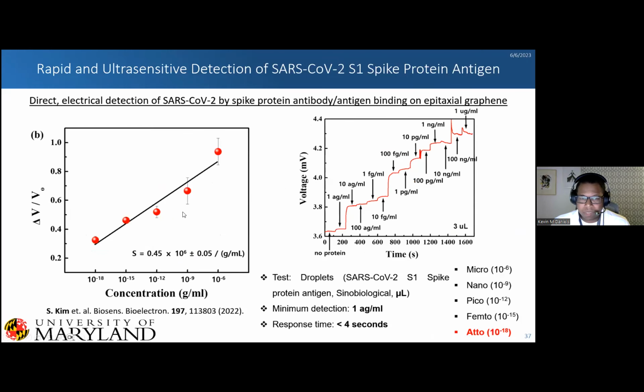And then how we can look at this is that we see a drop in our significance, our figure significance. So we did a t-test on each one of these points and noticed there was a breaking significance around 10 to the minus 15, going to 10 to the minus 12. So this is where people would typically start being able to detect bindings with a typical graphene field effect transistor, and this is where we're able to detect with our sensor. And so this breaking significance is significant because this is all controlled by strain. This is all controlled by typical charge transfer.